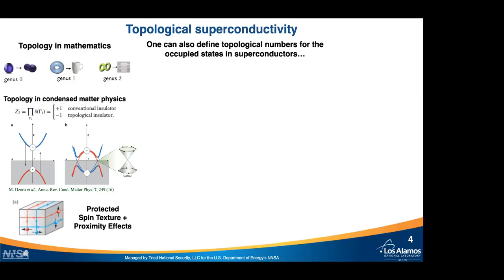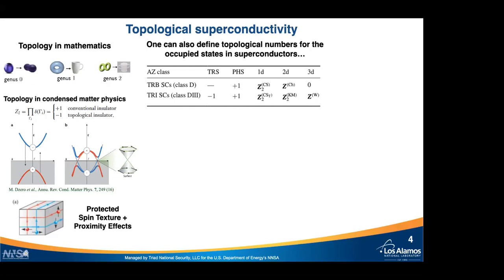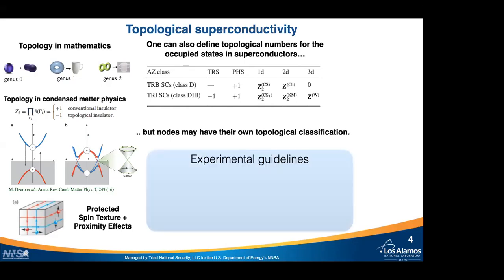And just the same way we described the topological classification of insulators, we can also define topological numbers for the occupied states in superconductors, but things get a little more complicated because we need to know, for example, if we have a quasi 1D, 2D, 3D system, if we have time reversal symmetry breaking or not, and on top of all of that, nodes in the superconducting order parameter may also have their own topological classification. So things are a bit more complicated. But that's when a combination of experimental intuition and theoretical background will be important. We know from theory that spin triplet superconductivity is particularly prone to host topological states. And we know from experiments that uranium-based superconductors, or 5f materials in general, tend to host spin triplet superconductivity.